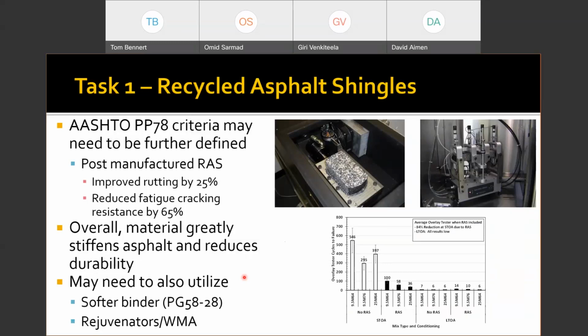Again, we're going through this study. We were looking at both products. The post-consumer had testing done on it to see whether or not there was asbestos in it, but both products are still too stiff to be used just as is without significantly doing a redesign of some kind. So in this case, this was an instance where we were looking at a recycled product, but it just didn't work. At least it didn't work under the current system without some significant modifications.